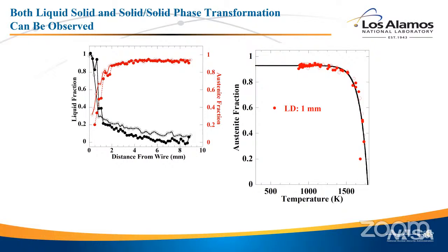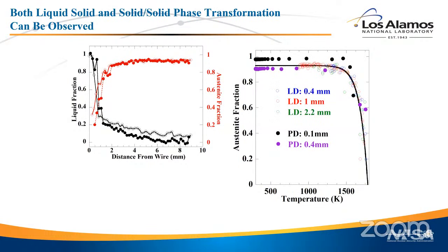So here you're looking at the solid-solid phase transformation. 1 millimeter is how far we were away from the base plate. So you can look at that as a function of distance, and it turns out it doesn't matter. The cooling rates are different as a function of distance from the base plate, but the temperature at which austenite transforms to ferrite is not. And if you compare by LD, I'm talking about line deposition, PD is point deposition. Remember, the point deposition, the cooling rate was about an order of magnitude faster. It was 1,000 degrees per second, 1,500 actually. In the line deposition, it was more like 100 degrees per second because we keep dumping in heat, right?